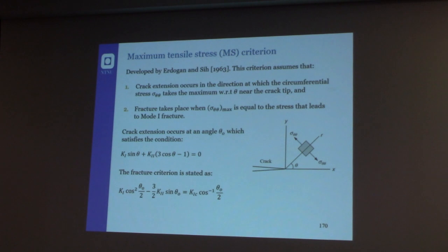And so what George C. Sih and Erdogan found out is that the crack tends to propagate when this equation is solved. So when the contribution of the stress due to mode 2 in this direction is equal to 0, and when locally a point or a cube of material is only subject to tensile loading. So locally there is no mode 2, and so the criterion is closed. It is also called the local mode 1 criterion. It's very simple because it's an imposition that locally you only maintain mode 1.